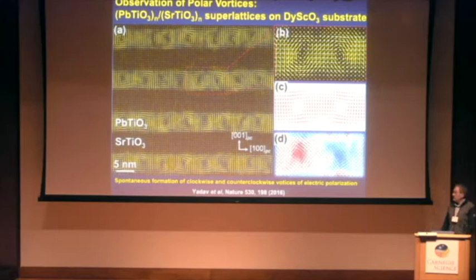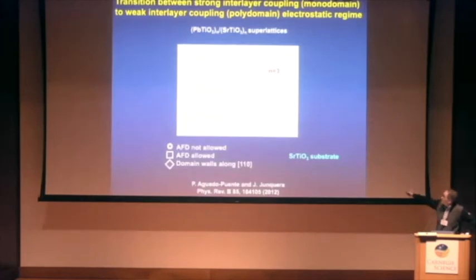The point is that we are at the limit of the things that we can do from first principles. In particular, this calculation here for 3 unit cells of lead titanate, 3 unit cells of strontium titanate, and 16 unit cells of periodicity for the domain includes of the order of 1,000 atoms, and it took more than 6 months to relax, single shot. So we cannot explore this kind of configurations in an easy way, and somehow we were forced to implement a new simulation method that we call second principles, and is already implemented in a code called Scale-Up.